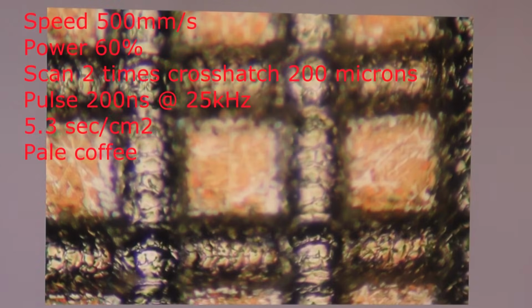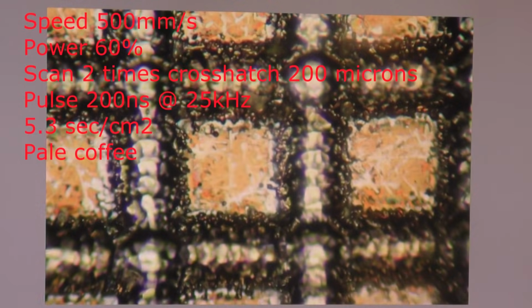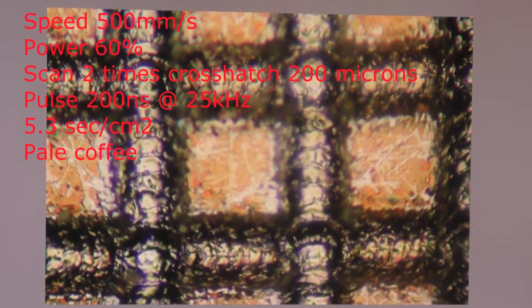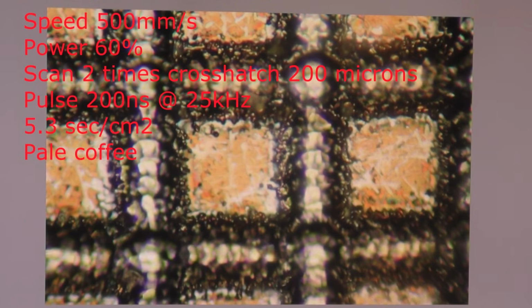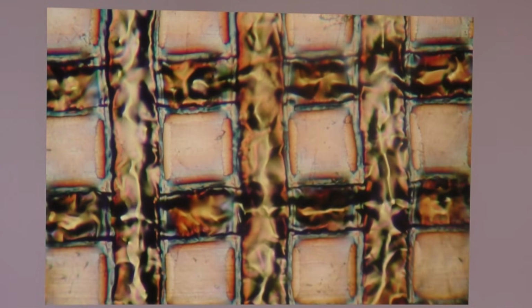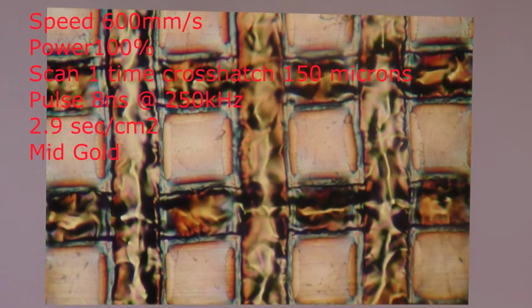So I'll drop the magnification down to 200 so that we can see things quite quickly. I'm just zooming in and out, moving the focus around just so that you get an idea of the fact that there is quite a lot of variation in the depth of these things. That's a sort of a latte colour, very light fawn. It's on the edge of a glittery gold, but it's a little bit less than a gold. Now isn't that beautiful? Now that's a mid gold.